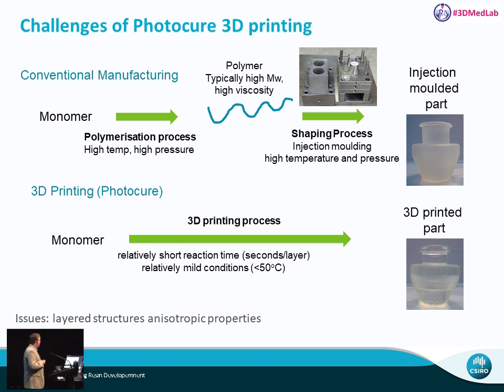If we compare that to 3D printing, in particular photocurable 3D printing, we're trying to do all these steps in one step. So we're going from monomer through to a 3D printed part. And we're doing it in a relatively short time under very mild conditions. Typically, for a photocurable process, we're doing exposure times of just a few seconds per layer, and under relatively mild conditions, room temperature up to maybe 70 degrees. So there's a lot of challenges in developing photocurable materials that can have the same properties as conventional materials. And that's made worse by the fact that the 3D printed structures are a layered structure, and therefore they have anisotropic properties.